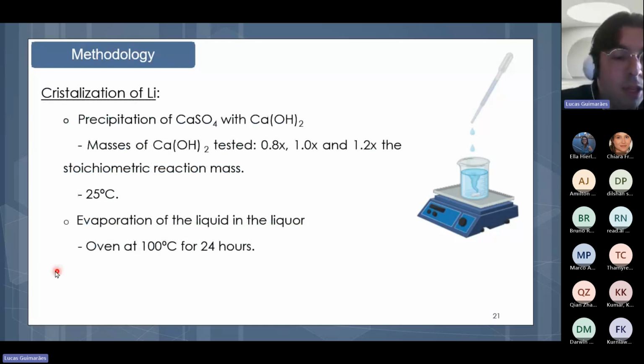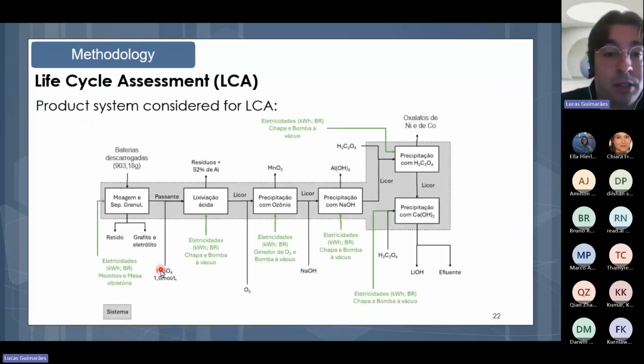For the crystallization of lithium, it was first prepared and studied a precipitation of calcium sulfate with the precipitating agent calcium hydroxide, and again a similar methodology to the previous one. The masses of calcium hydroxide tested were 0.8, 1, and 1.2 times the stoichiometric reaction mass, and the temperature studied was 25 degrees Celsius. And after that, the evaporation of the liquid in the liquor was performed in an oven at 100 degrees Celsius for 24 hours. And then it was possible to have the crystallized lithium in the lithium hydroxide form.